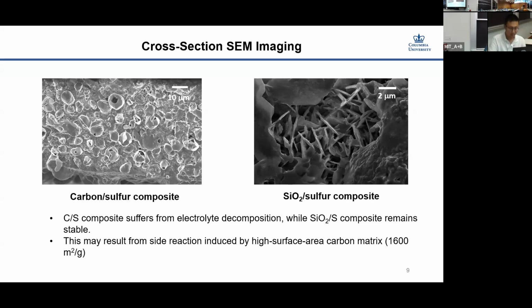And then you can ask, if it's insulating, how are you going to transfer electrons? The reason is that we still have some carbon black inside, and carbon tubes. Although they can also cause a little bit of decomposition of the electrolyte, it's not significant, because the surface area is much less than that of the carbon matrix. So we reach a balance point between the electron conductivity and the material decomposition.